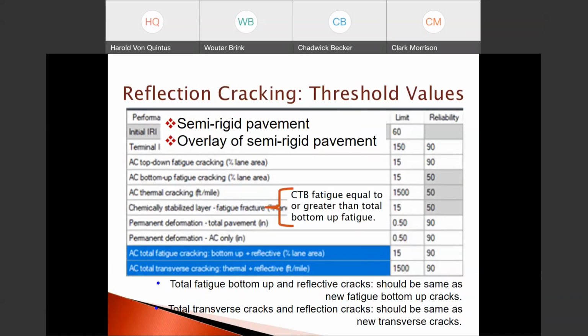For the semi-rigid pavements and or overlays of semi-rigid pavement, this shows the threshold values. And a little different here, where the total fatigue bottom up and reflective cracks should be the same as new fatigue bottom up cracks. The chemically stabilized layer, shown by the orange box, where the cement treated base fatigue threshold value is typically equal to or can be greater than the total bottom up fatigue cracking in the asphalt overlay. The transverse cracking would also be the same as new transverse cracks as shown on this slide.